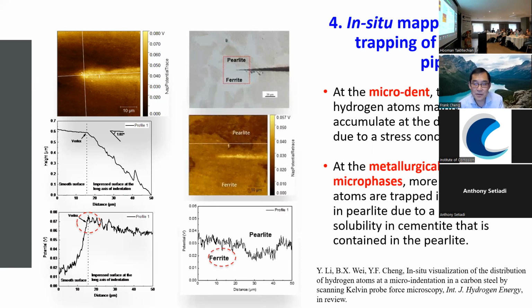The same thing, we can also use a technique to observe the different tendency of hydrogen atom accumulation in different metallurgical phases, such as pipeline steel, which mainly includes ferrite and pearlite. So the different metallurgical phases have a different tendency to trap hydrogen, based on the different colors in the middle graph in the slides. So anyhow, this slide just tells us that if we want to visualize the hydrogen distribution in the steel, we need to have certain surface analysis techniques, and this will give us the direct answer. If hydrogen goes into the steel, where will it stay.